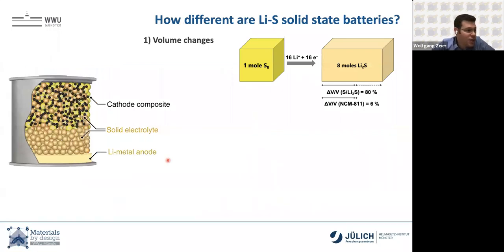So not using NCMs, or these intercalation type oxides, cathode active materials, but making it a bit more complicated. By a bit more complicated, meaning instead of having just an ionic conductor and a cathode active material, an oxide in there, we're now going into 3 phases where we have sulfur, we have carbon, we have our solid electrolytes. And there's a few major changes and challenges that come with this. The first one is your sulfur has really high volume changes. So if you convert sulfur to Li2S, you have an 80% volume increase. Whereas in these oxide materials it is only 6%.